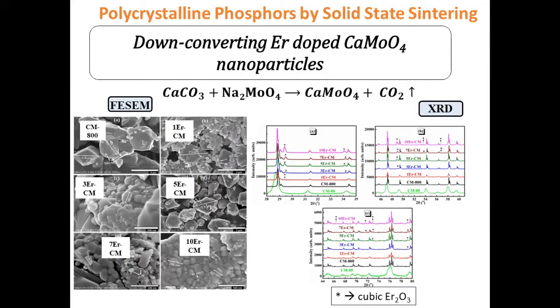So we have prepared erbium doped calcium molybdate. How we prepare them? Very simple. You take sodium molybdate and calcium carbonate. Sodium molybdate is a powder. Solid calcium carbonate is also a powder. You mix them in this appropriate molar ratio, and carbon dioxide will go out, and you will get calcium molybdate. This is the solid state method.